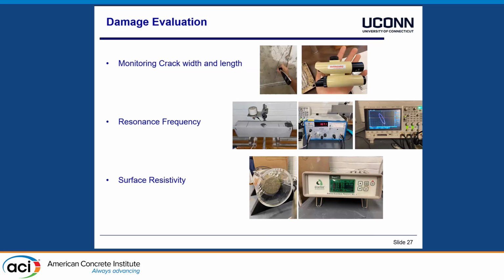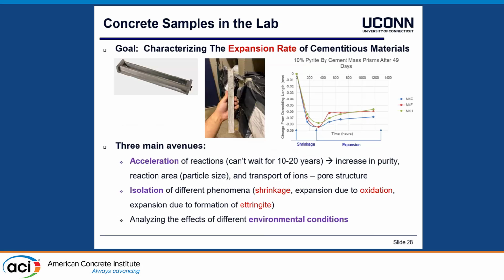We also do damage evaluation, using regular traditional crack measuring tools for crack width and crack length. And then we also explore resonance frequency and surface resistivity to evaluate the damage inside the concrete non-destructively. And then, of course, we do expansion tests in our lab where we use the mortar test.